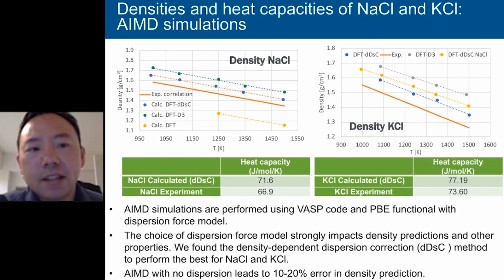So to begin with, the densities and heat capacities of sodium chloride and potassium chloride have been very carefully studied using Ab-Initio MD simulations. So essentially, David used several different methods to model the dispersion force. The important conclusion is that the Ab-Initio MD without any dispersion model has 10 to 20% error in predicting the density of these two simple salts.